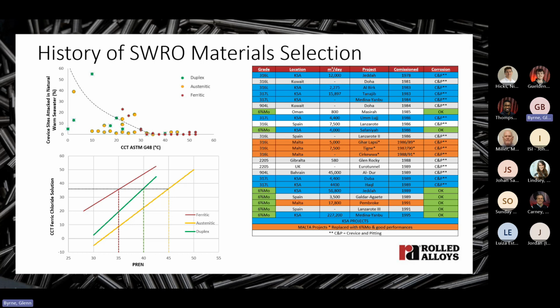In other projects, it took time before corrosion became a problem. 316 and 2205 and 904 alloys performance was mixed in the short term, but generally within 5 years it had widespread corrosion. There was still claim and counterclaim as to the usefulness of low-grade stainless steels, but with time their limitation became apparent, even in the cold seawater of the North Sea.